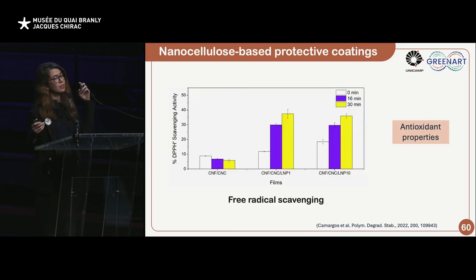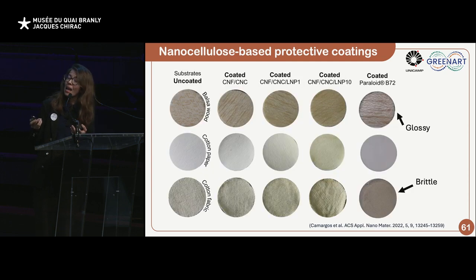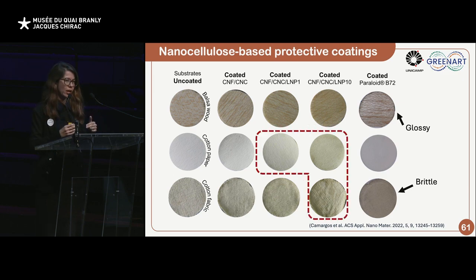Here we have some results regarding the antioxidant properties of the coatings. That is also very interesting to protect coated substrates against aging, the hydrothermal aging, for example. And here are some cellulosic mock-ups coated with this type of coating, the nanocellulose, nanolignin coatings, in comparison to mock-ups coated with Paraloid B72. And we can see here that for the wood sample, for example, the color is not an issue because the nanolignin does not change the color too much. But then when we consider the lighter color substrates, the color can be an issue. But we will have the answer in a few slides, okay?